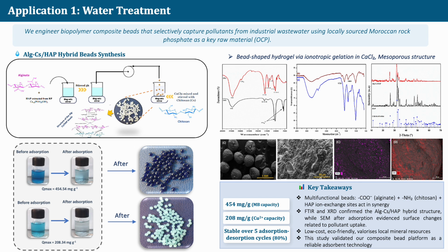After adsorption, SEM observations also showed visible changes on the bead's surface, supporting the interaction between the pollutants and the active sites of the composite. This synergy between carboxyl groups from alginate, amino groups from chitosan, and ion exchange sites from hydroxyapatite explains the high adsorption performance, reaching about 454 milligram per gram for methylene blue and 208 milligram per gram for copper ions.